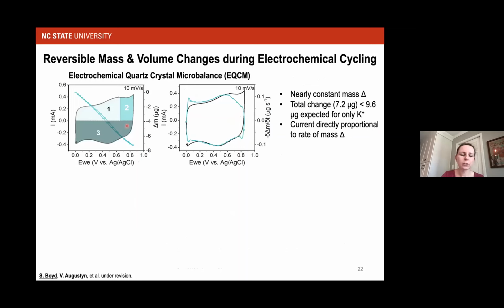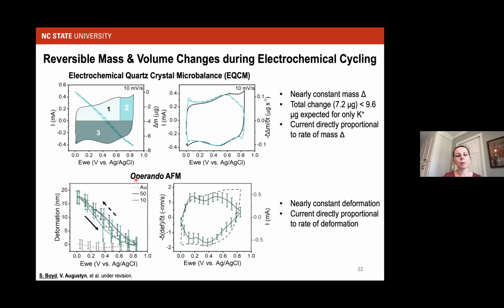Here's some more experimental evidence that just told us about how reversible the electrochemistry was. So this is electrochemical quartz crystal microbalance showing this almost linear change in mass as a function of applied potential with very little hysteresis. The change in mass was a little bit smaller than if we just expected potassium ions to be moving. So we think there is potassium ion insertion along with water deinsertion from the layers, like an exchange mechanism. And then we also applied an operando AFM technique where we measured the flexing, so the overall deformation of the electrode, and it also showed this really nice linear response.